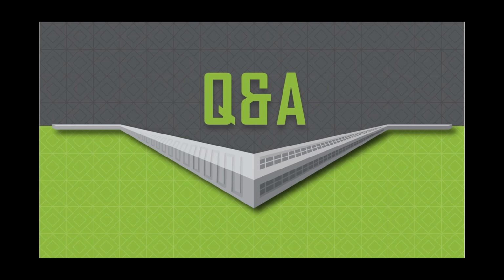I don't think we've done other studies, and we also know that the carbides are very critical for high temperature creep strength. So I think you need a combination of those two plus the base matrix composition. So maybe all three coming together to give the best creep strength. I think so. Again, I think the oxides are helping. I think the carbides are helping. I think the tungsten and rhenium segregation at the grain boundaries are helping, and it all leads to a much more robust material at high temperature.